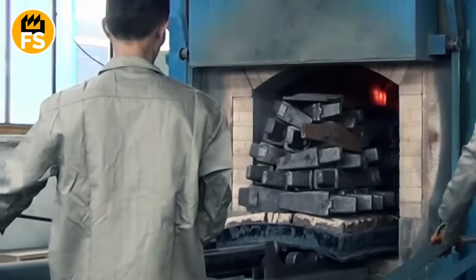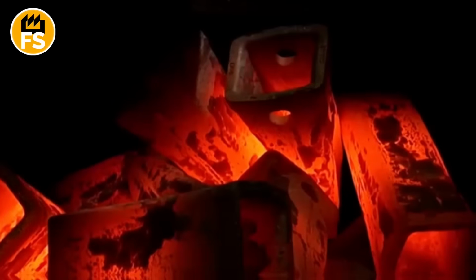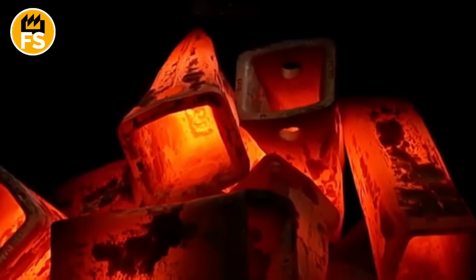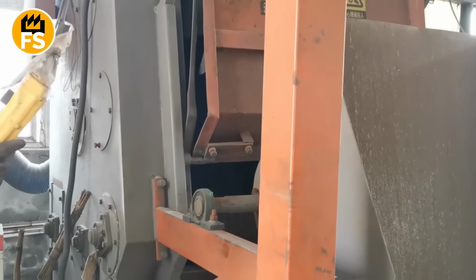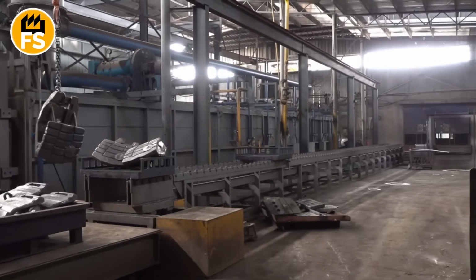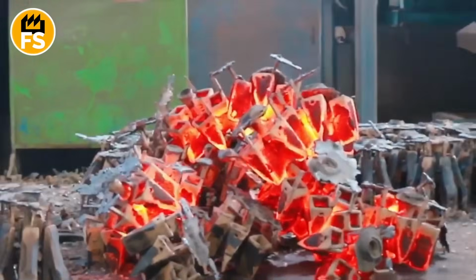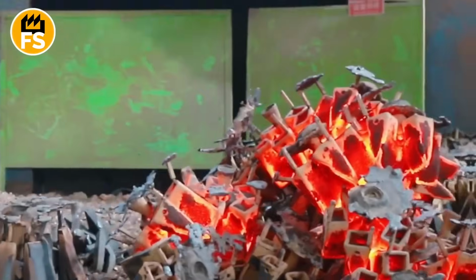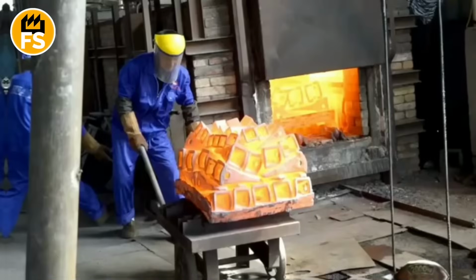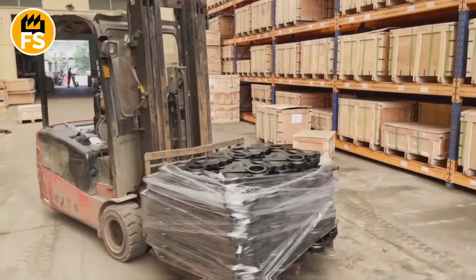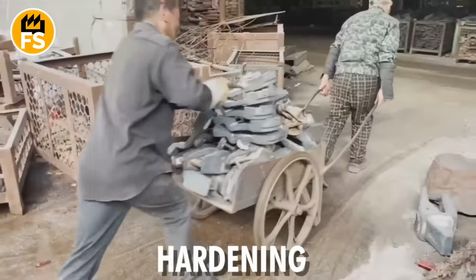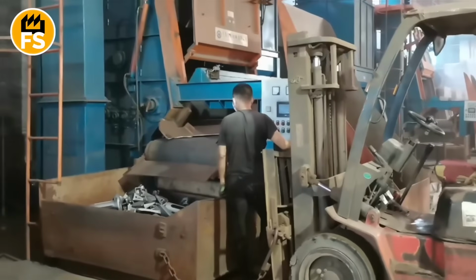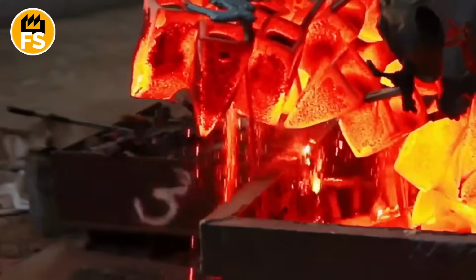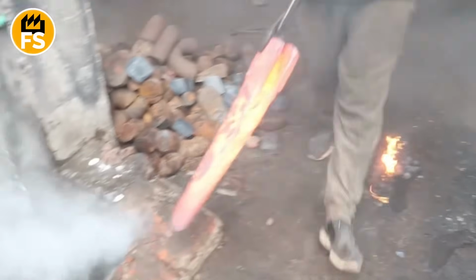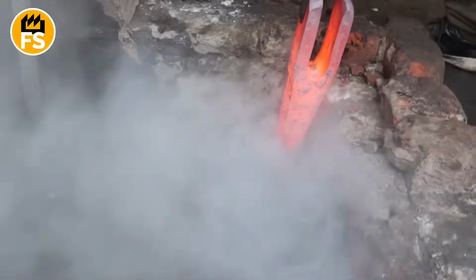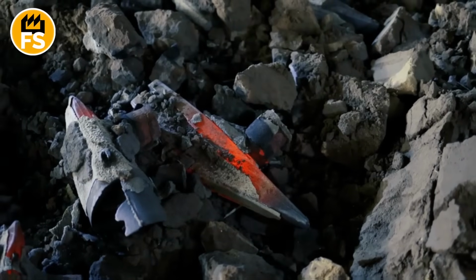Heat treatment. The teeth go into a furnace for normalizing. Here they're heated to 1920 to 2070 degrees Fahrenheit and held for 10 hours. This temperature lets the steel recrystallize, refining the grains and making the structure uniform. The metal becomes stronger and more elastic at the same time. After normalization comes the critical step, hardening. The teeth are heated again, this time to 1870 degrees Fahrenheit, then rapidly cooled in oil or water. This process transforms the steel's internal structure into martensite, a super hard crystalline form that can handle enormous loads.